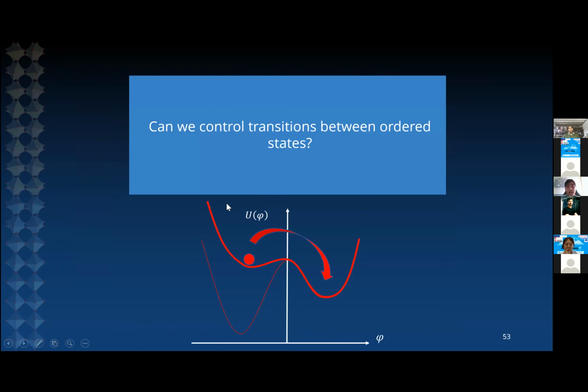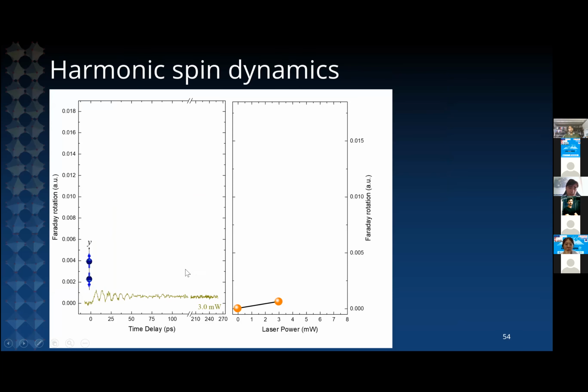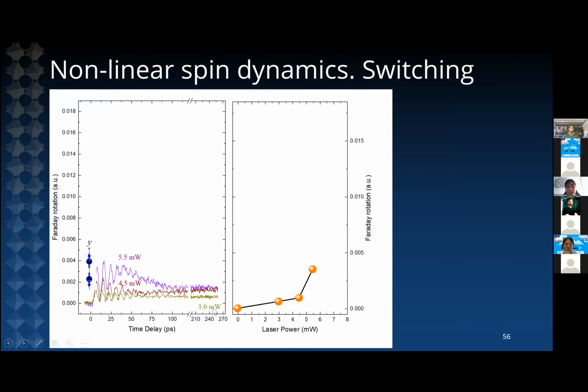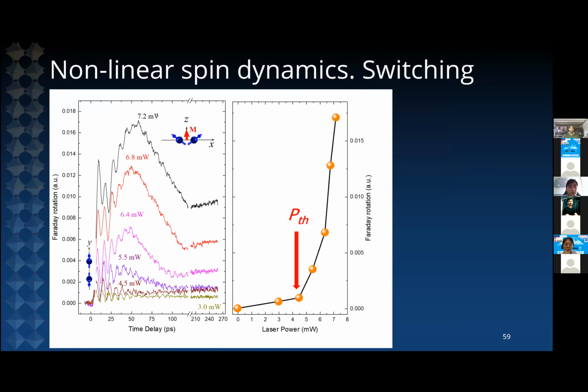Now the question is, can we also induce a transition to the competing weak ferromagnetic phase? And the answer is yes, but this requires a minimum amount of fluence. So if we excite the system gently with low fluence, we observe harmonic spin dynamics. But as we crank up the laser power at the phonon resonance, we start to observe an anharmonic response, a nonlinear spin dynamics, and the emergence of a net magnetization in the system measured by the Faraday rotation. So this indicates directly a transition from the antiferromagnetic state to the weakly ferromagnetic phase.